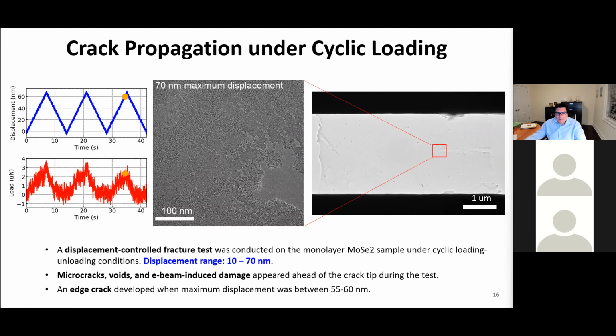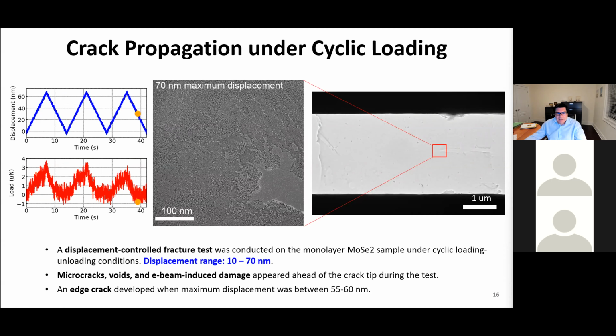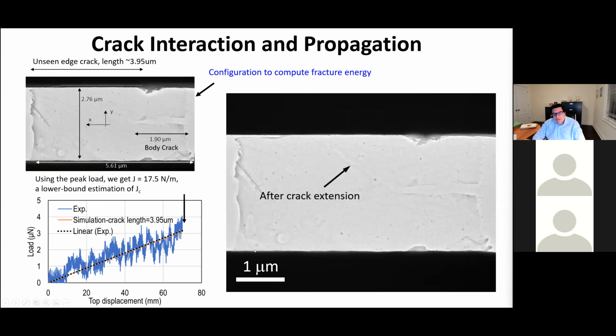But the crack did not propagate, and according to our understanding from the previous experiment, it should have propagated for the maximum far field displacements that were imposed. So at the end of the experiment, we saw spontaneously this crack propagation at an angle and realized that the geometry of the sample was more complex than our intended geometry, which is a strip with just one major crack that we will call the body crack.